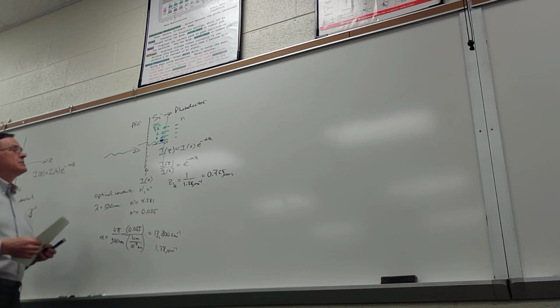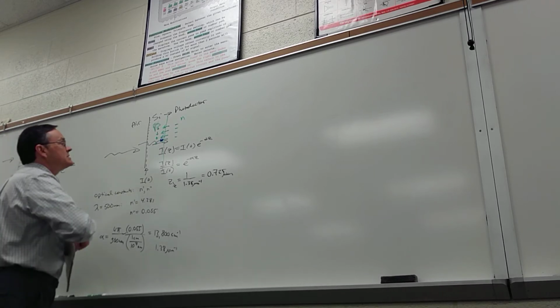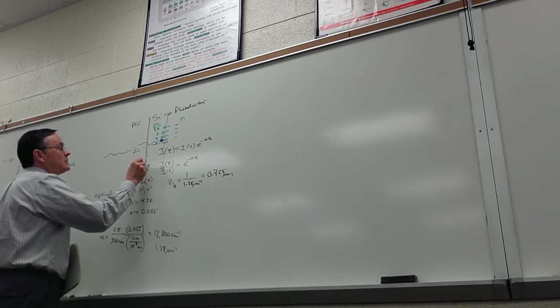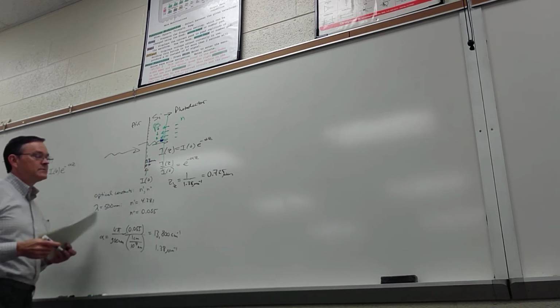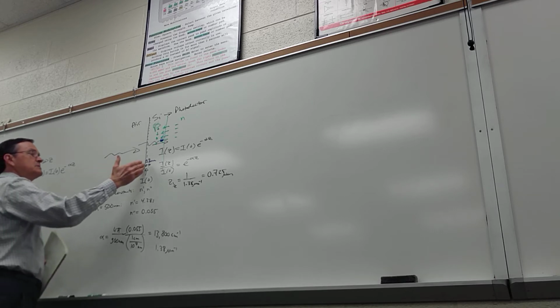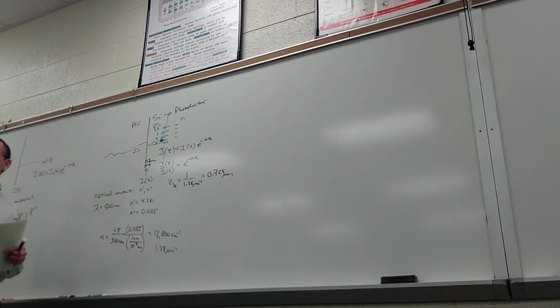So if my depletion region is, say, 5 microns underneath the surface, you're not going to get a thing, because all the absorption happens much closer to the surface. On the other hand, if my depletion region is, say, within 0.3 microns of the surface, it's not going to be very efficient because a lot of the absorption happens beyond 0.3 microns.